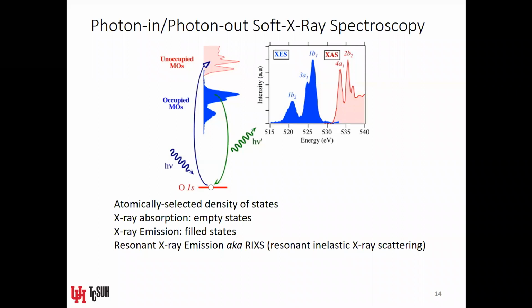So when you take a soft X-ray, for example, like the one given in blue on the left, and you tune it, let's say, to an oxygen 1s state, that energy, which should be around 530 electron volts, will excite an electron out of the core oxygen 1s state, and can excite it into an unoccupied state, okay? That process is an X-ray absorption process. And it's possible to measure this signal, meaning the flow of the electrons out of the core level into the unoccupied state, by connecting a drain current to your sample, okay? And collecting the current that is produced as a result of hitting it with the tuned soft X-rays. So it's possible to measure an X-ray absorption signature, okay?